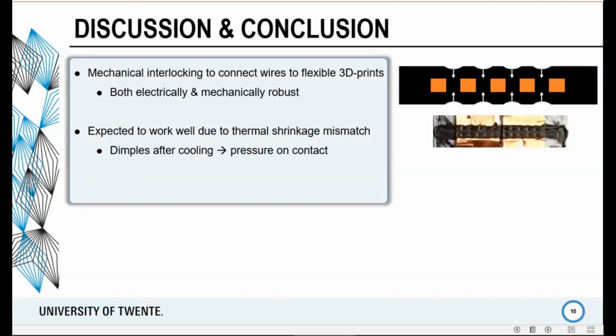Then the polymer shrinks after cooling down. The polymer shrinks a lot more than the copper, which gives this pressure on your contact. So the polymer really squeezes around your copper contacts from all sides. And this pressure, we believe, helps in improving or lowering the contact resistance, basically.